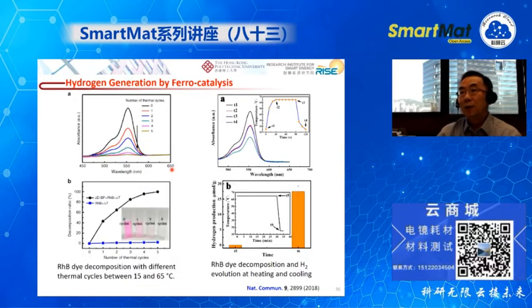And we also found that the black phosphorus can also be used for dye decomposition, and we found it is really a pyroelectric effect.